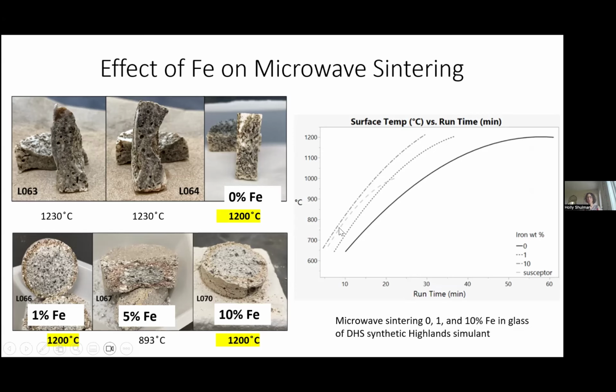This line here is the optical pyrometer on the susceptor. And you can see that it's vigorous heating at first, but it's not heating as high as that high iron simulant. And this is also intentional, that we design these susceptors so that we don't want them to continue to heat. We want them to turn over and not compete for microwave energy. So that's why I say it's even better if you have a source that you can just turn off, that it's not related to the microwave at all.